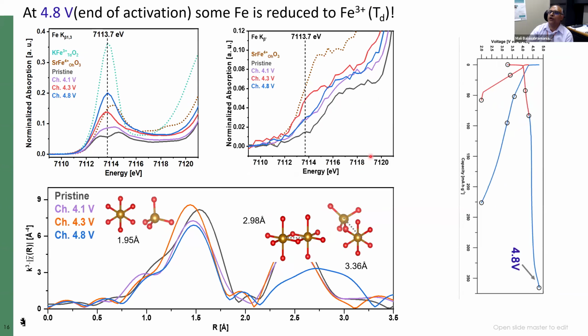Now, if we go to 4.8 volts at the end of activation, where we believe something else happens, we see that relative to 4.3 volts, which is this blue line now, this feature actually comes down in intensity, and it becomes somewhat comparable to what you see at 4.1 volts. This clearly shows that some of the iron 4+ character is lost. This could be unexpected, because you are actually oxidizing the material, removing lithium from the compound as you are charging.